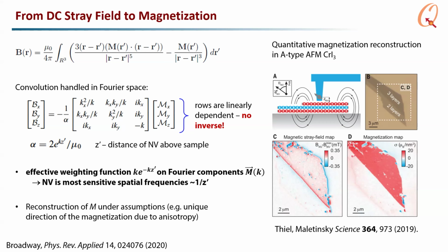So this was most famously done for 2D chromium iodide by Patrick's group, where chromium triiodide is an A-type antiferromagnet. So even layers should have compensated magnetizations, and odd layers should have a single uncompensated magnetization. So here you see a 2-layer, 3-layer sample, and you only see magnetic field from the 3-layer sections. And using this inverse, by assuming that the magnetization is in the z direction, you can get the quantitative magnetization density.